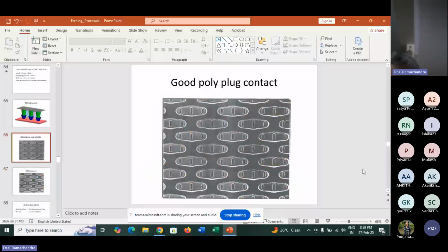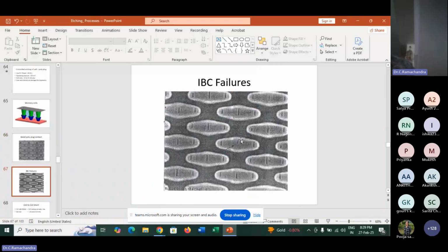See, after removing all these things, this is what we call the moat. And this is the imprint that you are seeing. So when you remove every layer successfully, if this imprint is there, that means my polyplug had a good contact. If it is not there, there is a failure. And we have taken some failed devices. We have seen exactly which location had failed, and we have done a similar process. Now you see the imprint is missing compared to this good location. Here see the imprint. So this is a failed bit, and here the imprint is weak. So this was the technology we have developed.